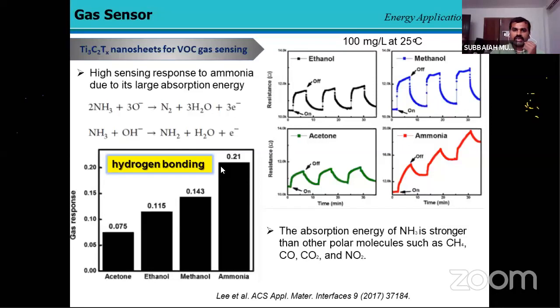The MXene moiety has the functional groups of hydroxide and oxide on the edges as well as basal planes of MXene, which tend to form hydrogen bonding. Among these, ammonia has higher sensing responses due to large absorption energy, which was confirmed by DFT studies also. The absorption energy of ammonia is stronger than the other molecules, such as methane, carbon monoxide, carbon dioxide, and nitrogen dioxides